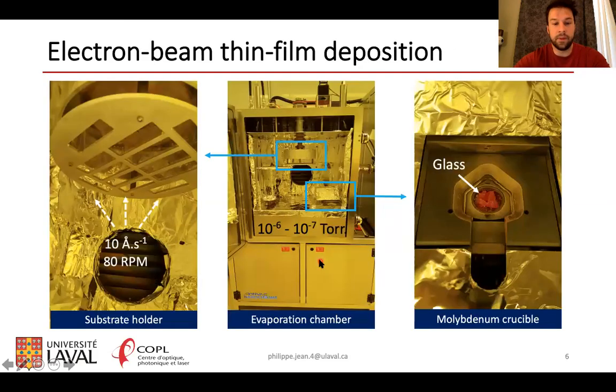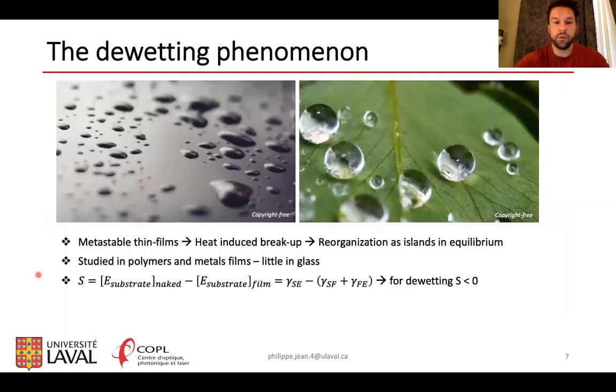So next, we deposited thin film of chalcogenide using electron beam evaporation. In the middle, you can see our evaporation chamber with the substrate holder, the electron beam source, and here you can see the chalcogenide glass inside the molybdenum crucible. Here you can see the substrate holder that was rotated at 80 RPM, and the deposition rate we use is 10 angstrom per second. So next, the last step in our process is a thermal dewetting step.